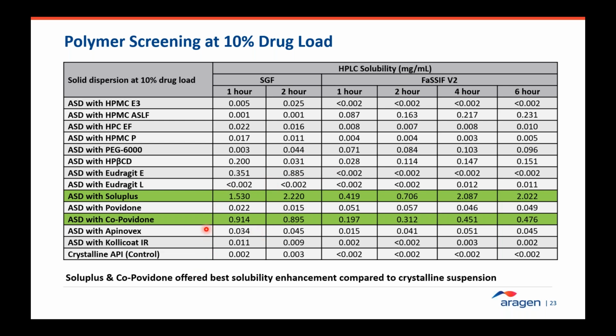So from this list, as you can see, Soluplus and copovidone showed the best improvement in the solubility compared to most other polymers, mainly considering the solubility in FaSSIF, with Soluplus being the best and closely followed by copovidone. So we pick these two polymers and combine them with increased drug load. As we increase the drug load, usually the solubility gets compromised. And that's when we include a surfactant to hold the supersaturation further and make several combinations until we are able to stabilize the solubility levels at a higher drug load.